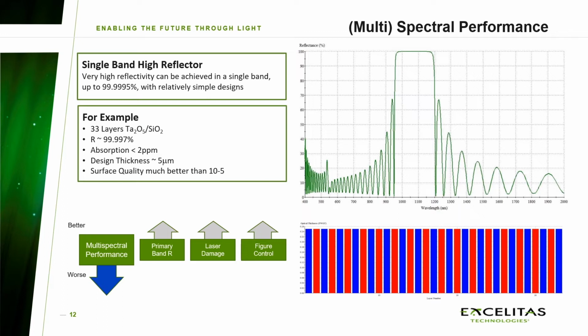With this simple design, we can achieve reflectivity levels that are almost 99.999. They're actually 99.997. So a very high reflectivity. The thickness of this design is very manageable, about 5 microns total thickness, and its absorption levels are very low. It can be made with very high surface quality. So this is going to be a really high quality reflector for a laser application. Unfortunately, it only reflects in one band.